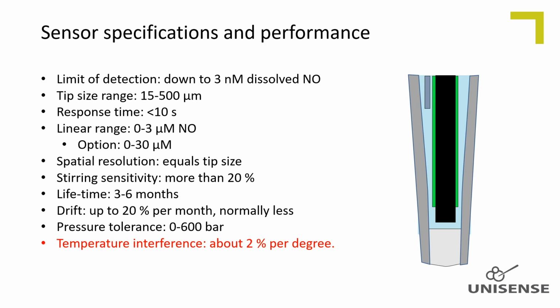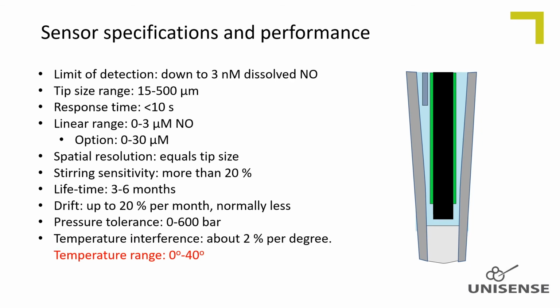In the web lecture about amperometric microsensors, the temperature influence is discussed in detail, and it is explained there why temperature compensation is difficult for amperometric microsensors. Temperature interference is about 2% per degree Celsius. We therefore recommend calibrating the nitric oxide sensor and measuring at the same temperature. The sensors can be used from 0 to 40 degrees Celsius.